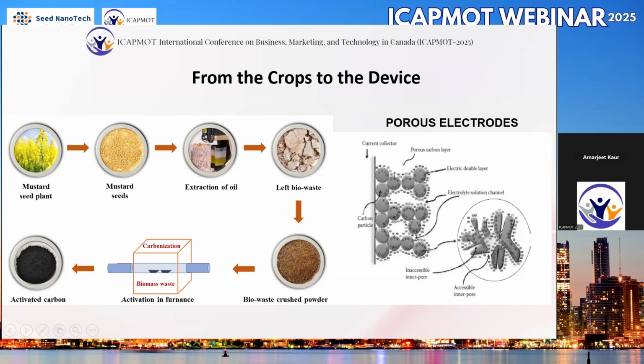Once we use a porous electrode, the charge gets trapped in these pores. As a result, the surface area available for charge trapping increases, and hence the total amount of charge trapped at the electrodes increases. This is the main reason for using these kinds of porous electrodes. So that is how we are making the porous carbon electrodes.